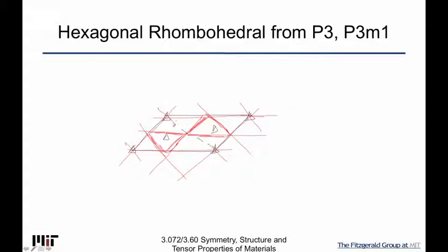And what you can clearly see from this is that the environment around this threefold axis in these bow ties and the environment here are different, right? These have all the mirror planes passing through because they're through the edges, where these have them around them. And so I cannot move onto here, and that's why this ends up still giving me the hexagonal. I only have the option of going straight up, and this only gives me the option of hexagonal primitive. So there's only two choices in all these cases.